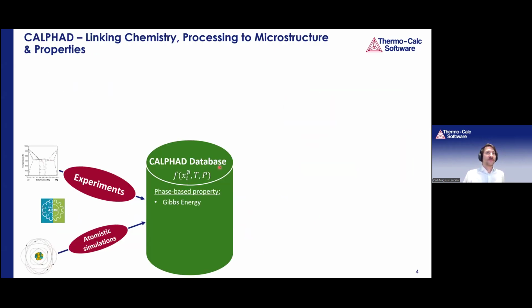And now I'll give a bit of an overview of the databases that are the foundation of these predictions that we can make in Thermocalc. So these are CALPHAD databases. CALPHAD stands for calculation of phase diagrams, and we work with phase-based properties. These properties are evaluated for all phases that can appear in a type of alloy. They are developed using experimental data and also atomistic simulations, and they are described as a function of chemistry, temperature, and to a limited extent also pressure.